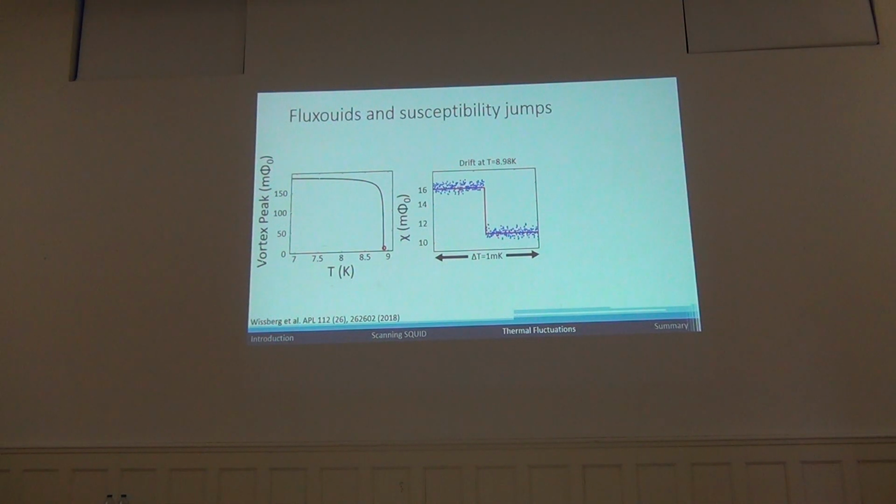So when you think about it, this is basically a natural manifestation of the way superconductors shield magnetic field. When you apply magnetic field to a sample, you induce supercurrents, and these supercurrents must flow in closed paths. Therefore, they must maintain flux quantization. So basically, every sensitive susceptibility measurement should detect discrete levels originating from an addition or subtraction of an individual fluxoid.